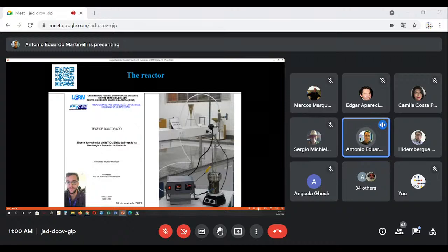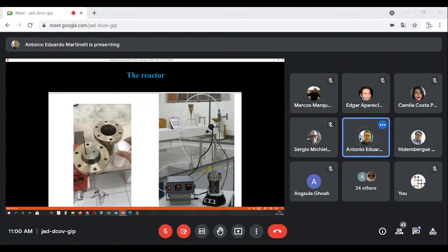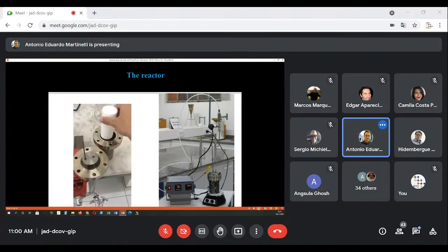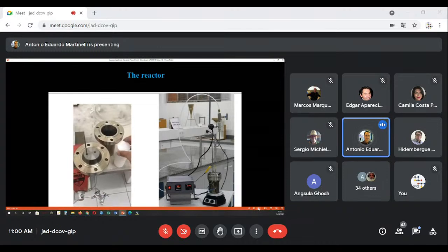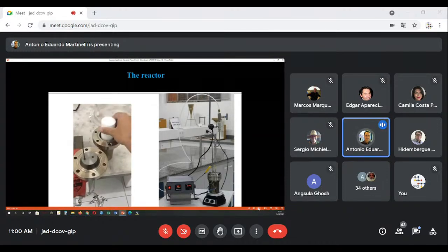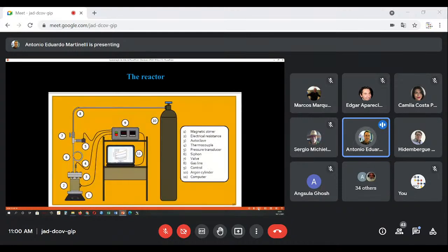Okay, so this is the original work, the original PhD thesis by Armando Monte Mendes. He's now a postdoc here in our group and continues to use the reactor he designed, which is shown in this picture here. Here we have an example of a solution being put in a Teflon liner and inside the reactor where the synthesis will take place. This is the schematic of the whole system. Here we have a magnetic stirrer and electrical resistance to heat the reactor, an autoclave to apply pressure, a thermocouple to control temperature, a pressure transducer.